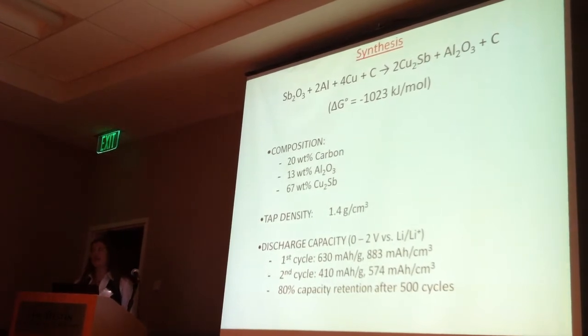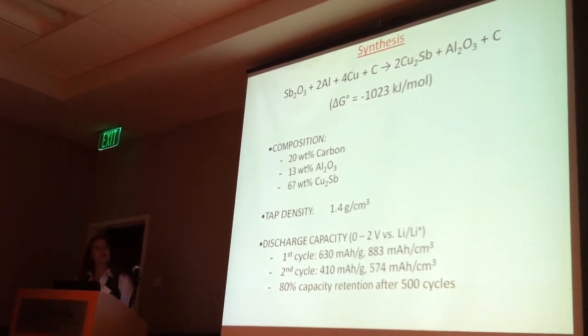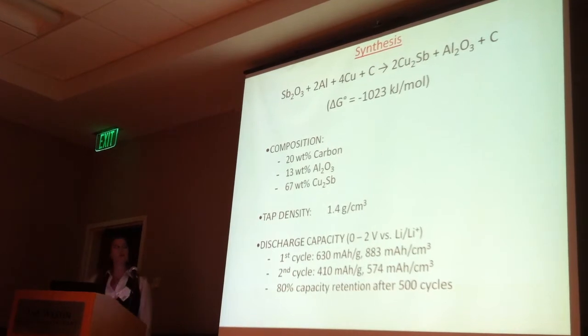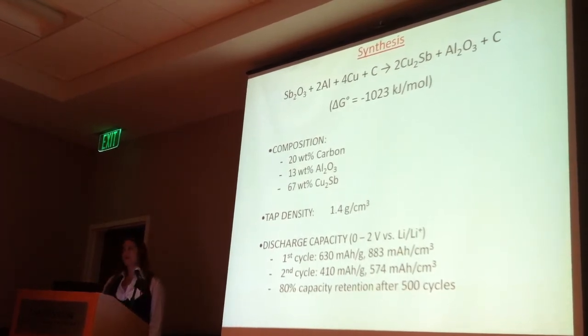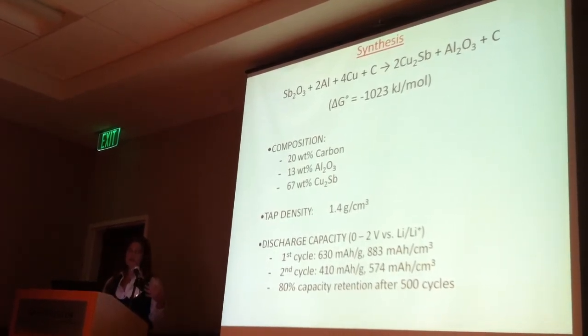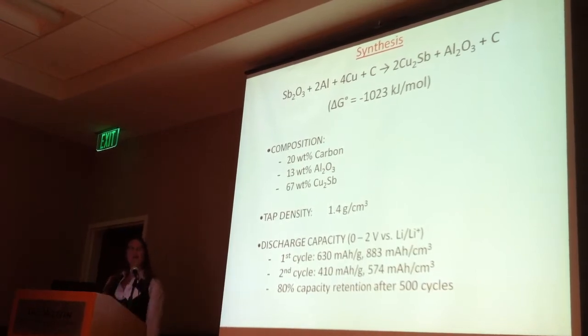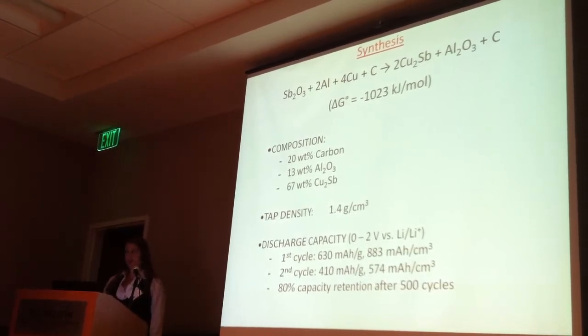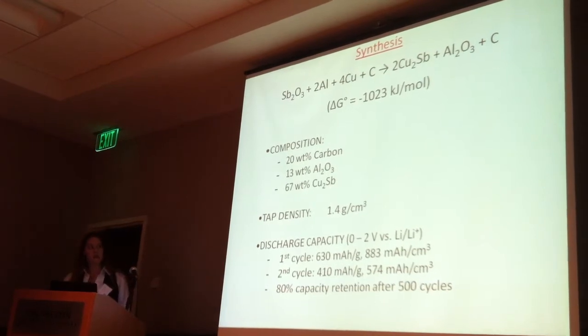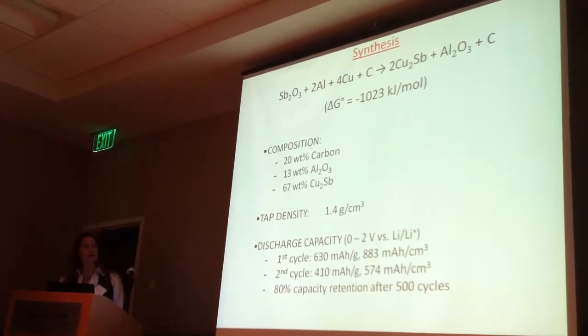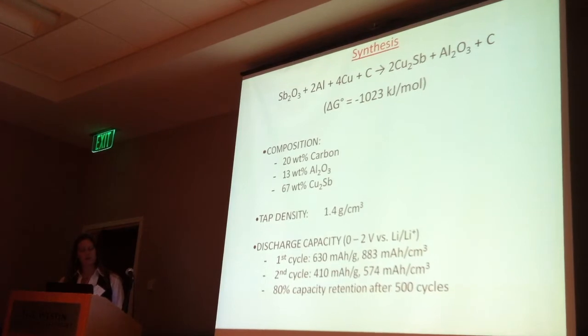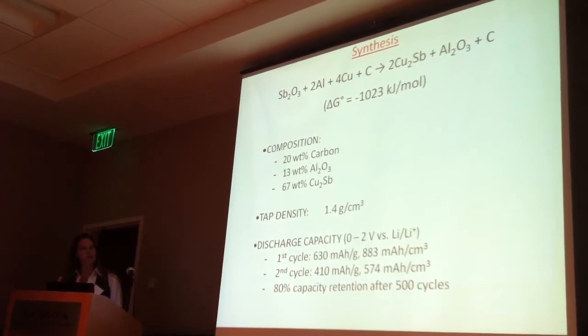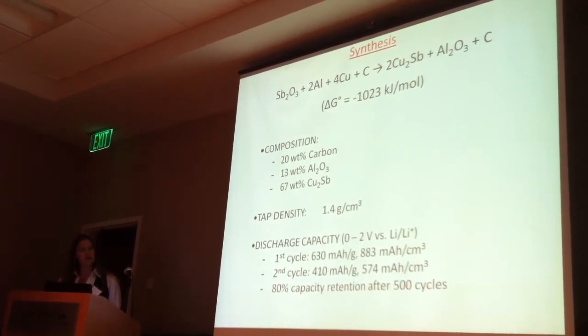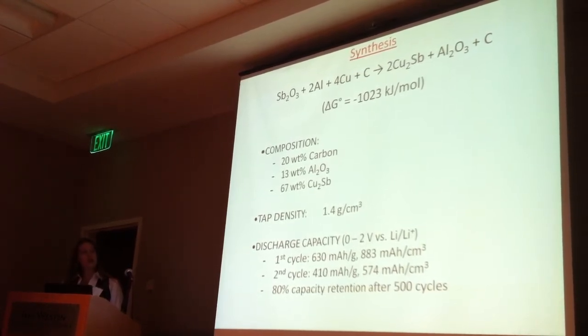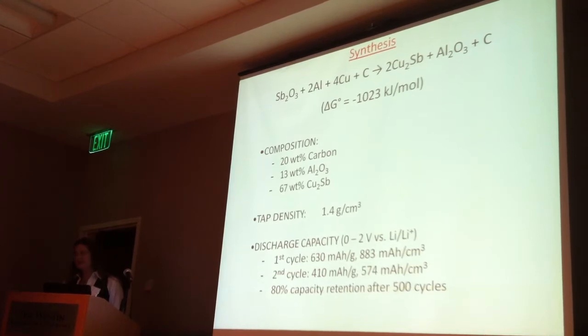Acetylene black is the carbon that we use for these materials. And what we found is a material with higher tap density than commercial graphite. Commercial graphite that we tested was from 0.6 to 1 grams per centimeter cubed, so we've got about a 40% increase in tap density, which translates to higher volumetric capacity over graphite. Also, our discharge capacities were 630 milliamp hours per gram in the first cycle and 410 milliamp hours per gram in the second cycle. And you notice that there's a difference there.